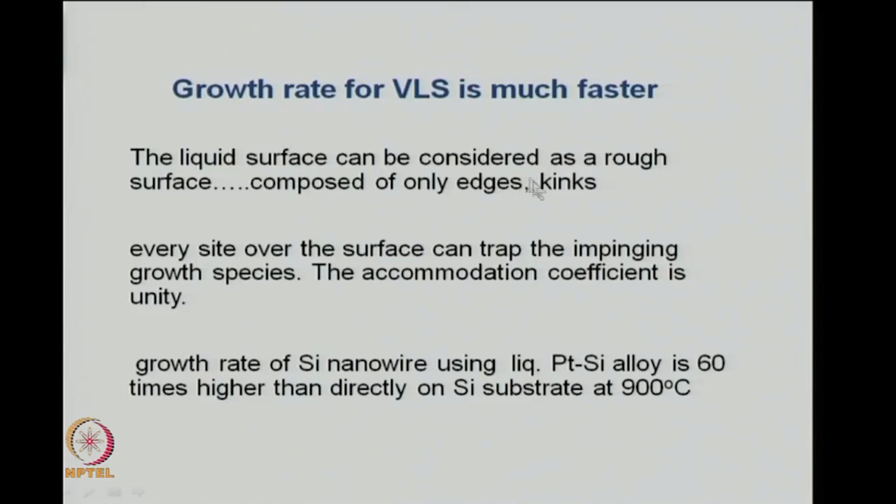There are some preferred sites where the gas molecules will be accommodated, and hence the accommodation coefficient on a solid surface will be much lower than on a liquid. So the liquid surface can be considered a rough surface composed of only edges and kinks, and that means every point can act to accommodate the incoming gaseous molecules.